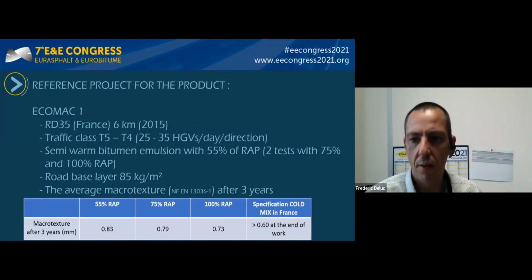We shall now consider the two construction projects. The first process, known as ECOMAC First, was laid on a 6 kilometer length of road on the RD 35 County Road in France. The level of traffic of this pavement is 25 to 35 HGVs per day and per direction. On most of this site, the semi-warm bitumen emulsion mix contained 55% of RAP, but two test sections were also laid with 75% and 100% of RAP.